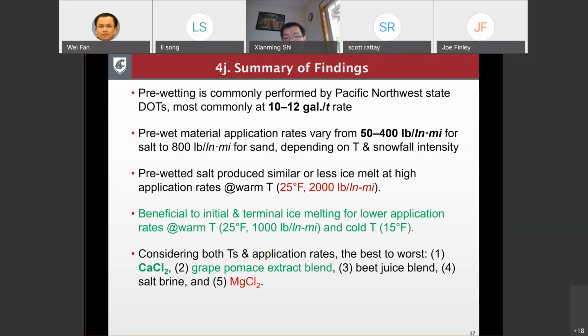Considering both temperatures and application rates, the best to worst list is here. The calcium chloride brine is the best pre-wetting liquid, and I have to add a disclaimer, under the investigated conditions in the lab. And then the grape pomace extract, the second, and then the beet juice blend, and then salt brine, and the worst was magnesium chloride. One thing to clarify is that in the lab, the relative humidity is about 20%. So the worst performance of mag chloride is not due to the hygroscopic nature. It's not grabbing much moisture from the air. And also calcium chloride is similar to magnesium chloride in terms of being hygroscopic, but that seems to not be the reason.